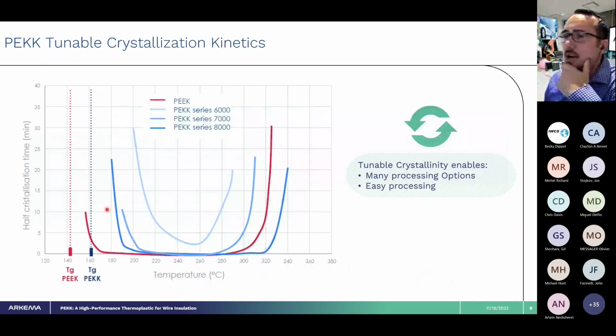Now, an area I mentioned previously is the crystallinity kinetics. By increasing the T to I ratio, or normalizing it closer to 60-40, you can actually slow the crystallization kinetics down so that you can retain an amorphous polymer, or do a controlled crystallization or controlled anneal. So what you're looking at here is essentially the half-life crystallization time versus the temperature.